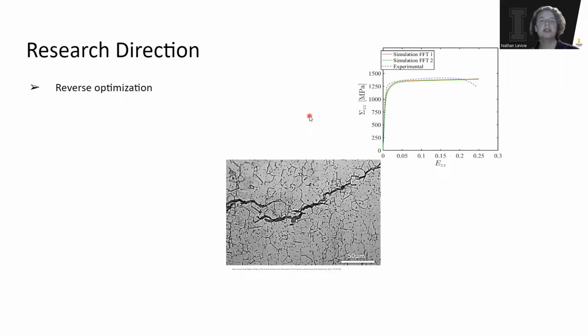In addition, subroutines need to be added to introduce voids and model damage to incorporate necking and fracturing. That is not even taken into account because the curve just keeps on going straight. But with the incorporation of subroutines, that would fit the model better. But as of currently, our main focus was grain size and the selective laser melting nature.